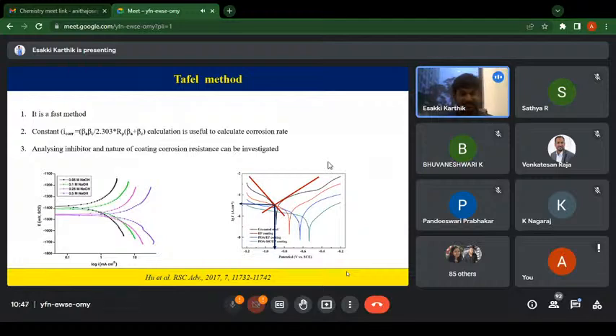When you do Tafel analysis, here I have mentioned stainless steel in different concentrations, from 0.05 molar NaOH to 0.5 molar NaOH. When I run the corrosion, of course 0.5 molar has higher corrosion compared to 0.05 molar NaOH, because when we increase the basicity, the corrosion rate will increase. You have two types of parameters: one is corrosion potential, another is corrosion current. How do you calculate them? On my right-hand side, in the Tafel plot, when you take the tangent lines of that Tafel plot, where they merge together, on the potential axis that is the corrosion potential, and on the current axis that is called the corrosion current.